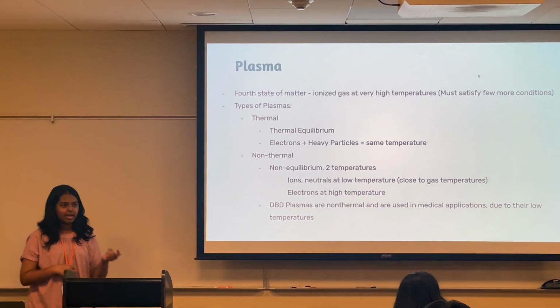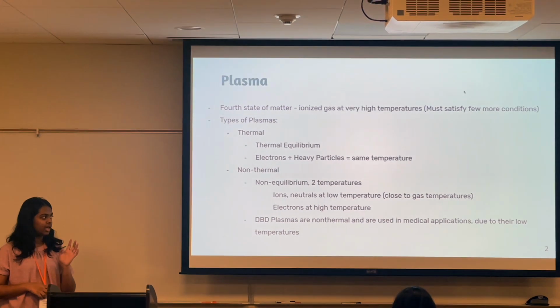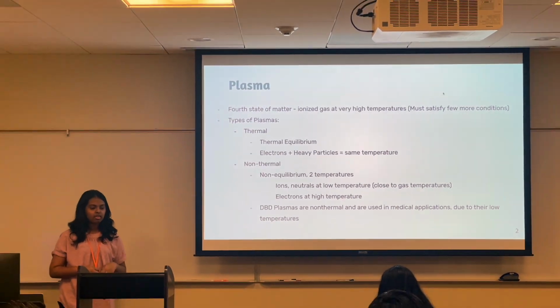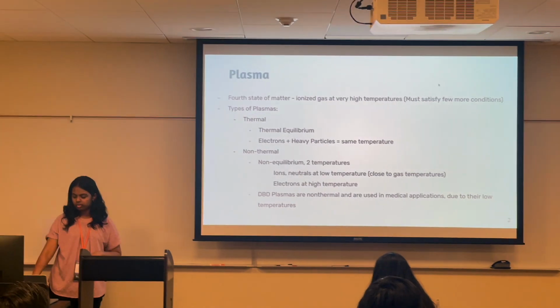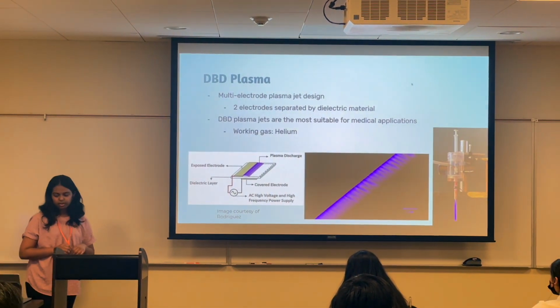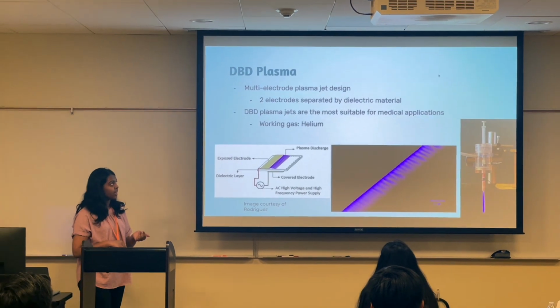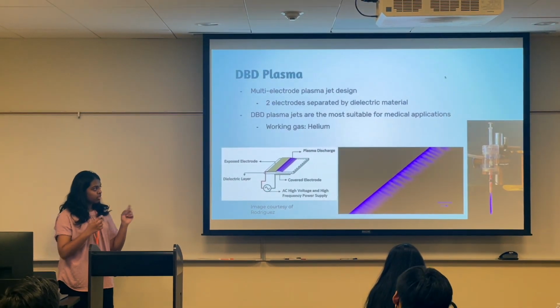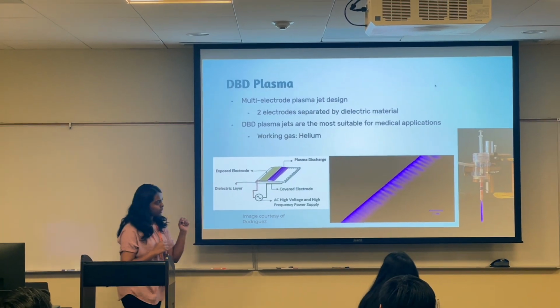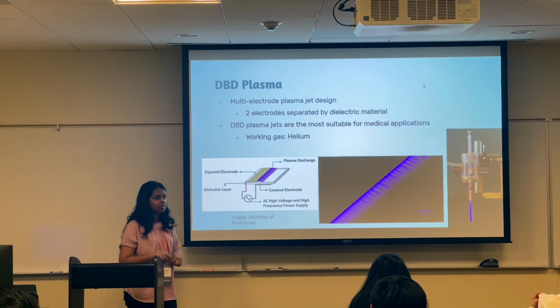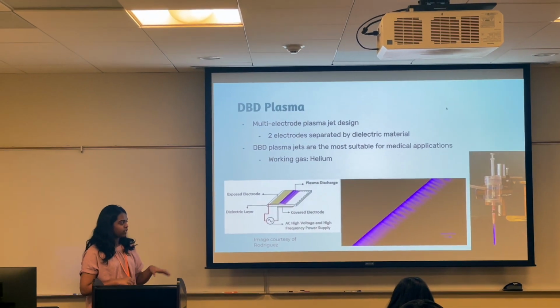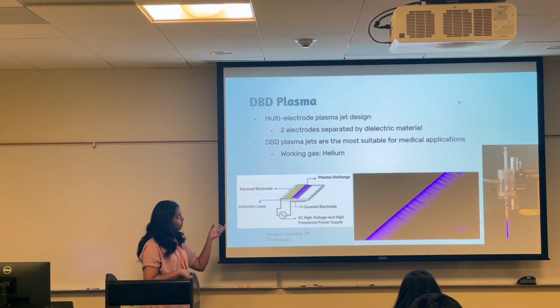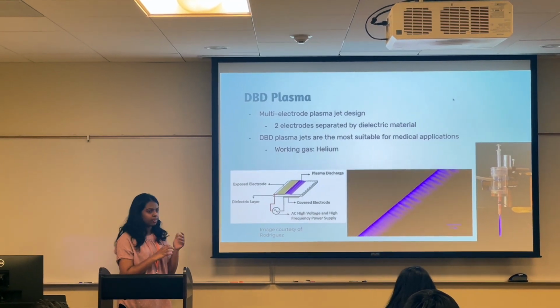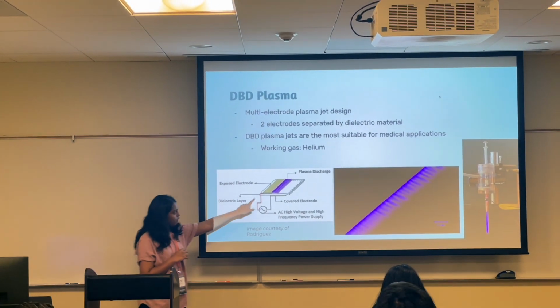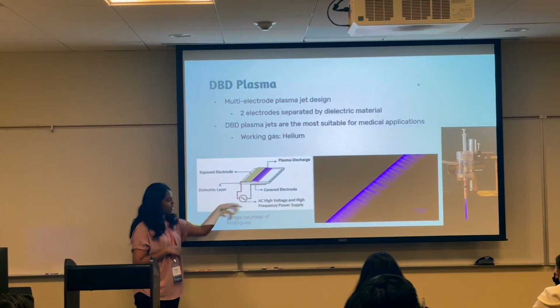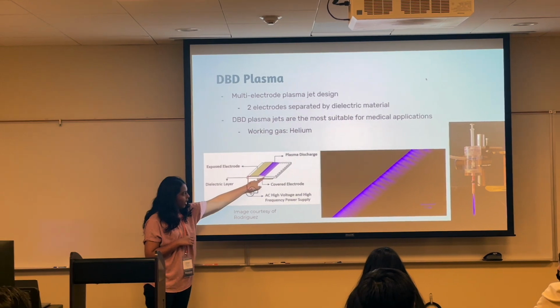And DBD plasma, or dielectric barrier discharge plasma, is non-thermal, and it's used in medical applications because it has generally low temperatures. So for our experiment, we decided to use a multi-electrode plasma jet designed with two electrodes separated by a dielectric material. That over there on the bottom right of this presentation is the multi-electrode plasma torch, and this over here is a good representation of how the separation of dielectric material goes. So we have over here our dielectric material, and on both sides we have an electrode, and this is the plasma that's coming out.